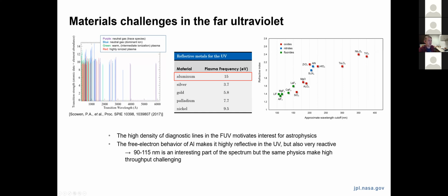In other words, as you approach that ground state energy, you run out of metals that are reflective. You run out of metals that have a high enough plasma frequency that they can produce a meaningful response at these short wavelengths. So aluminum is kind of your only metal of choice to operate in this wavelength range. And you run out of transparent oxide materials that have a band energy that's higher than that ground state energy.